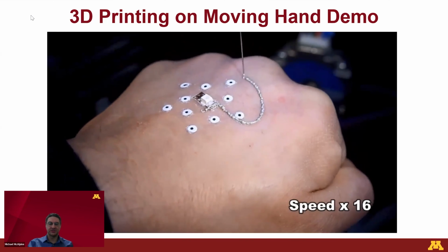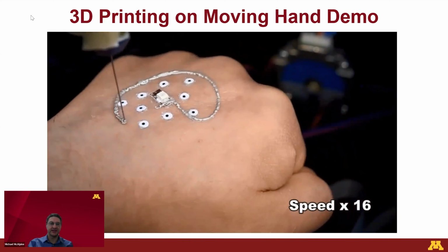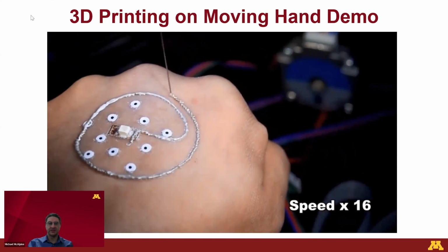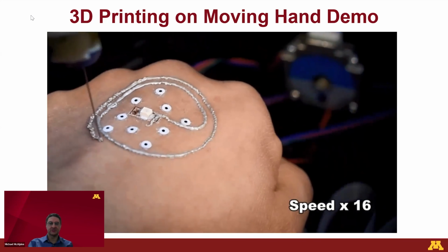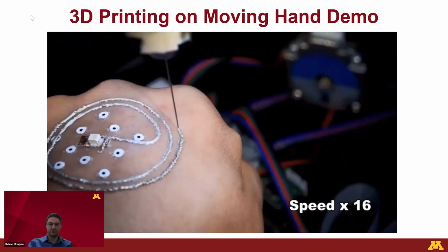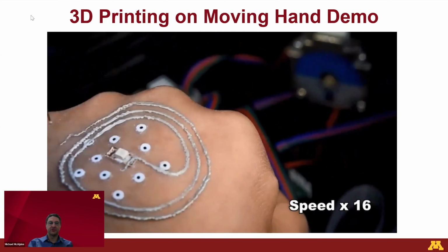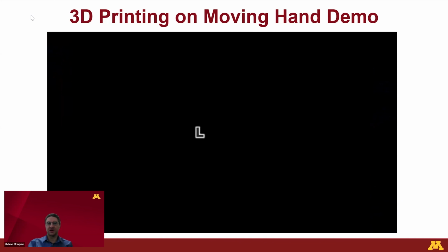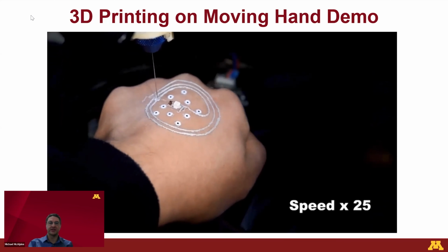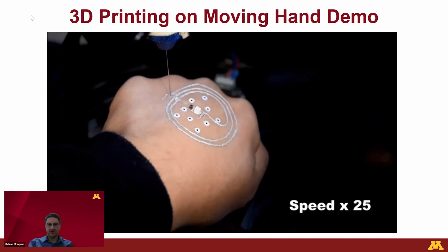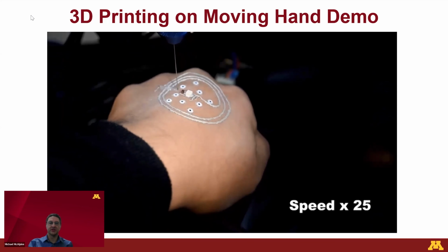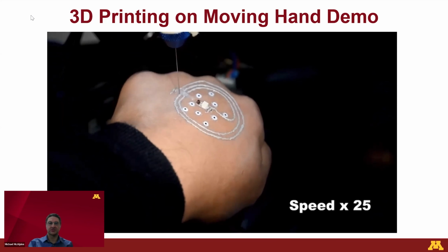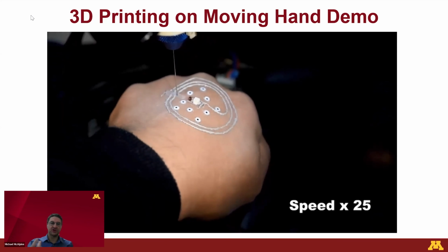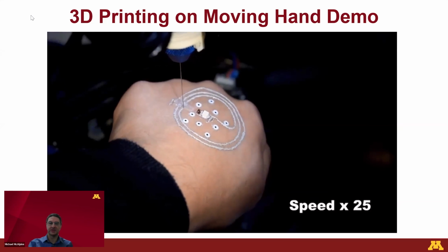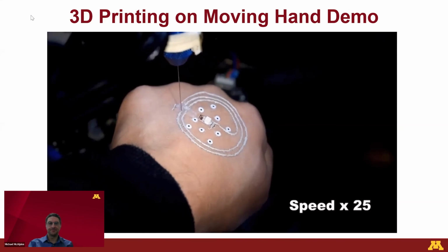And there's the silver ink that we're printing, and we're forming an antenna that connects to the LED. And this movie is sped up, but the hand, as you can see, is moving, and it's moving in completely random orientations during this process. It's not some type of periodic predictable motion. It's just random. But the printer is following those tracking markers and compensating for those, so that you can essentially deposit these various inks directly on the back of the hand to print an electronic circuit that connects to the LED that we placed in that first step there.